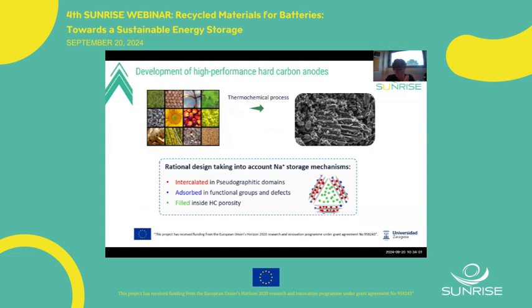For that, we need to rationally design these carbons, taking into account the different sodium ion storage mechanisms. It's known that sodium can be stored in hard carbon through three different mechanisms: intercalation between the graphitic or pseudo-graphitic domains, adsorption in the functional groups and defects on the surface of the carbon, and fitting inside the porosity of the hard carbon.